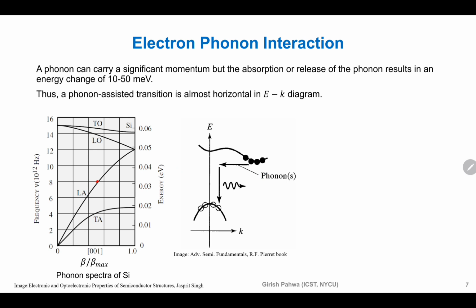So what they will prefer in an indirect band gap semiconductor is to jump through mid gap states. So there are these mid gap states. Okay. So electron, because now you have created a mid gap state, can first go from here to here, and then they can come to the valence band.